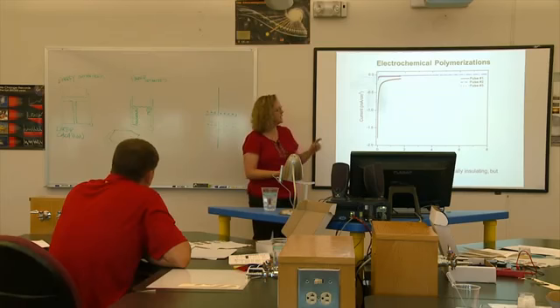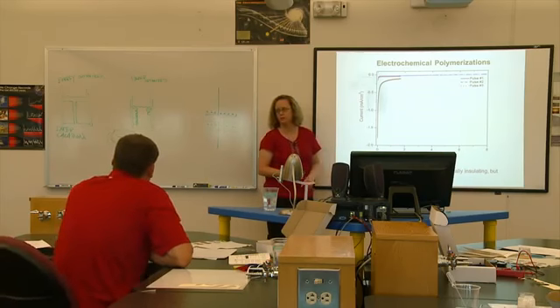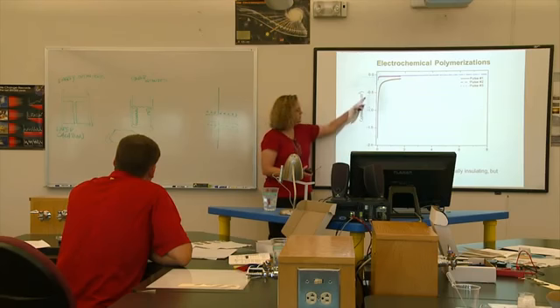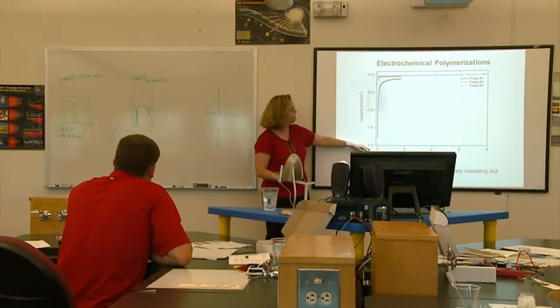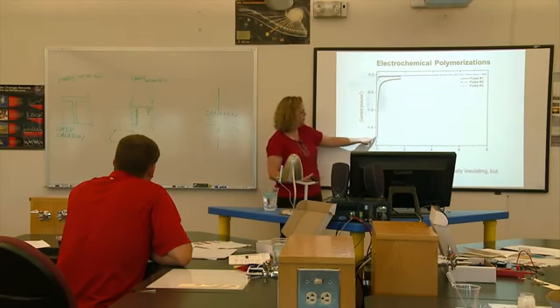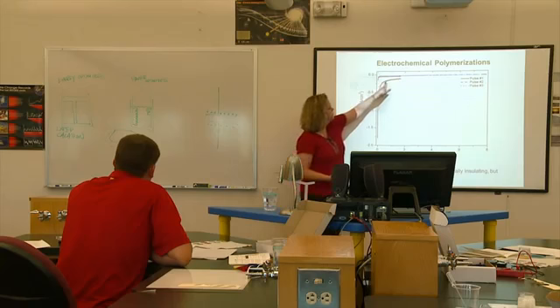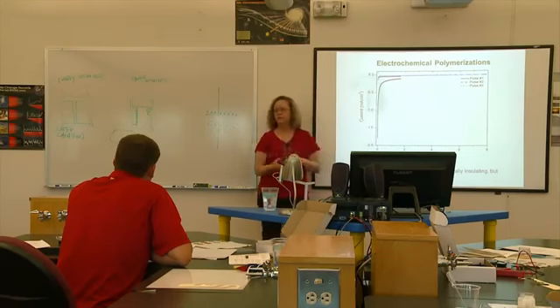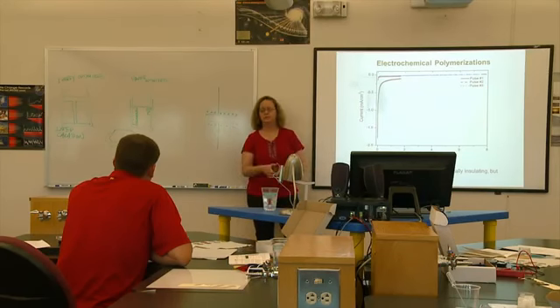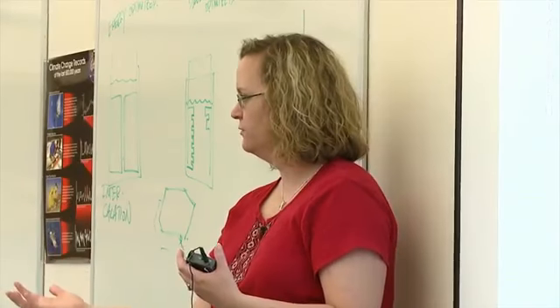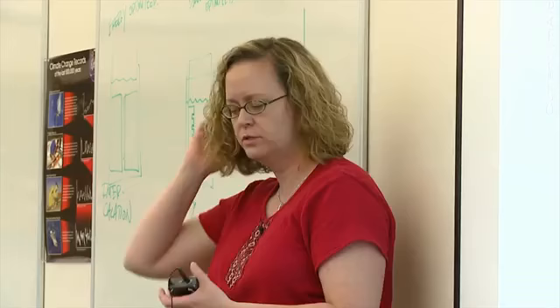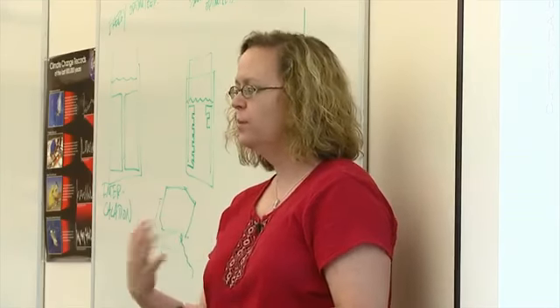If you look at the black line, this is the first pulse. We measure current as a function of time, and this is 0, and we're going to negative current because we're doing a reduction. So you see that the current starts high because a lot of polymer is being made. Then it drops pretty quickly and it evens out. Then we let it rest because with these weird shapes, the liquid needs time to replenish itself. So we turn the voltage off, we let everything rest, then we pulse again.